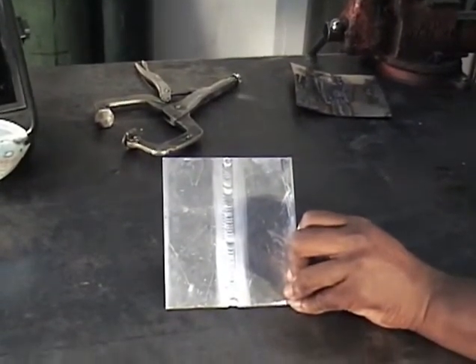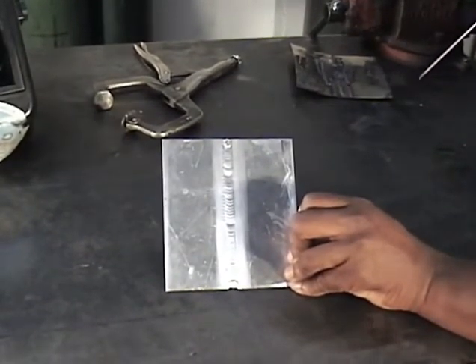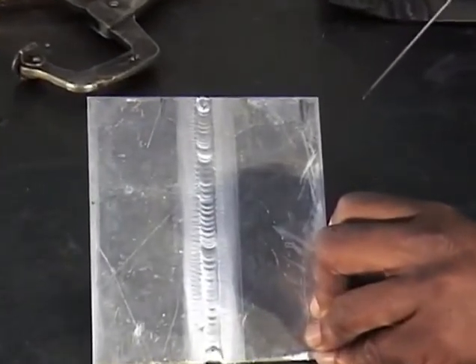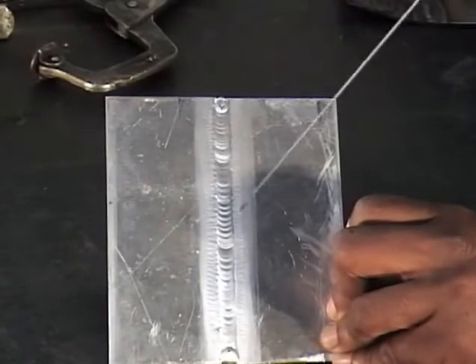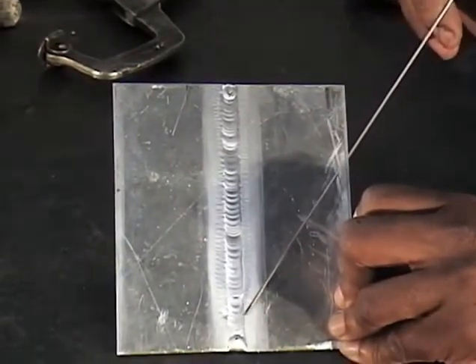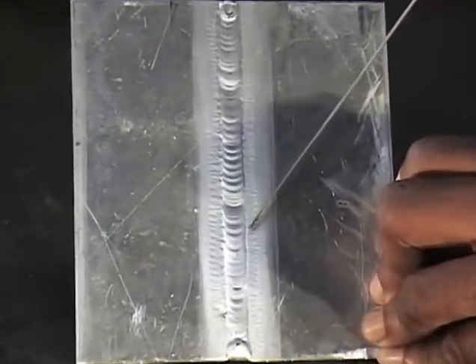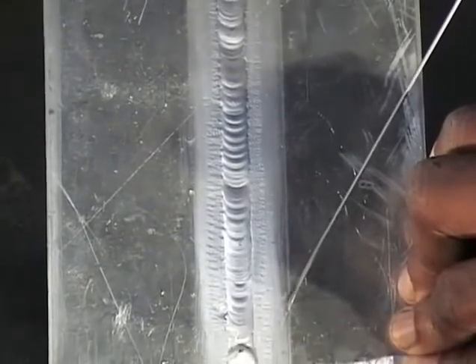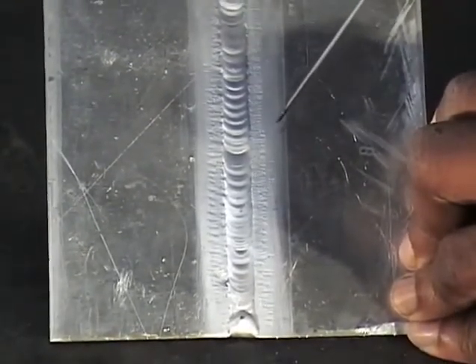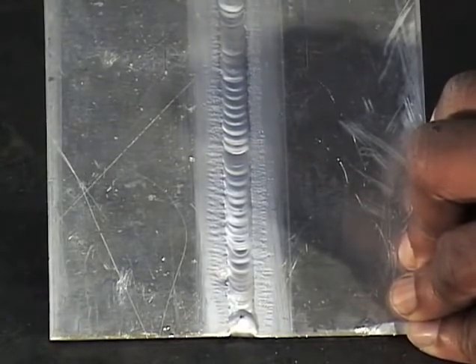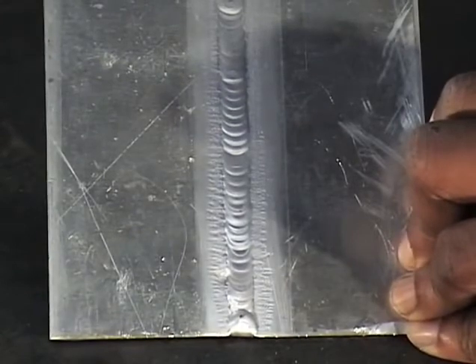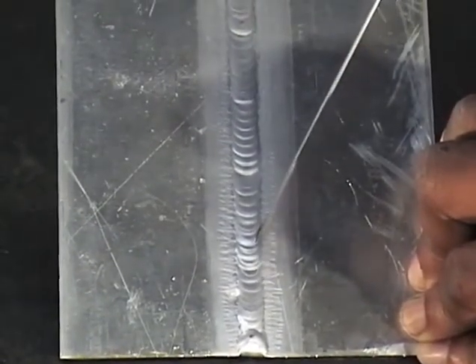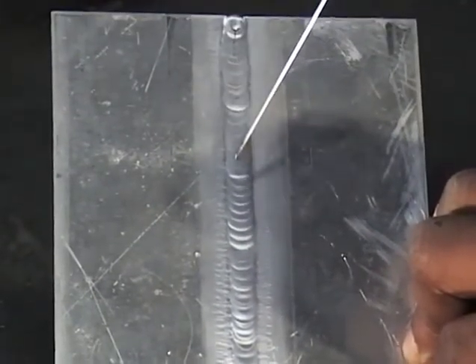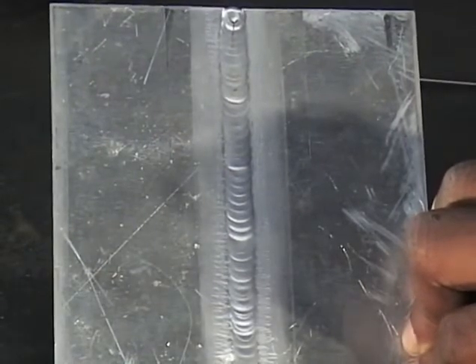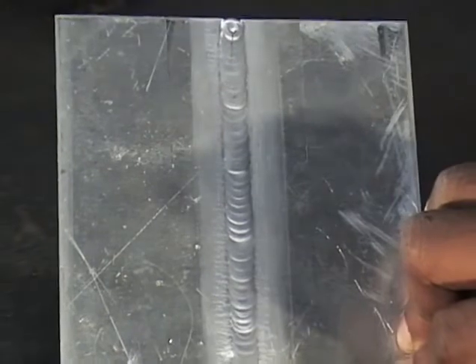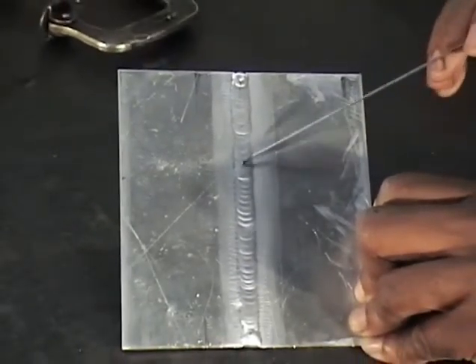Okay, we just finished welding our aluminum in the DC polarity. This is 6061 T6 aluminum. And this is what a finished weld should look like. Each weld bead locked behind the other. And aluminum being welded DC is not like welding at AC. You just light the torch and start running. AC, you have to sit there and let the part heat up for a while, but DC gives you a driving force in the material, and the heat is there immediately. As soon as you light the torch, it's there and it's ready to go. And that is what a finished weld should look like. And you want that crown of that weld to stick up 10% proud of the parent material. Again, the parent material is the sides of the plates, and the weld is in the center of the plate.